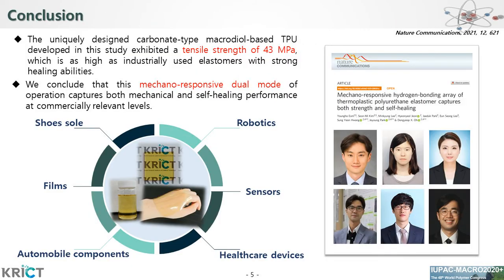In summary, the uniquely designed carbonate-type macrodiol-based TPU developed in this study exhibited a tensile strength of 43 MPa with strong healing abilities. This carbonate-type TPU exhibited strain-induced hardening and crystallization in dynamic mode due to a transformation toward the ordered mechanoresponsive hydrogen-bonded array, responsible for strong and tough properties observed in the stretching state.